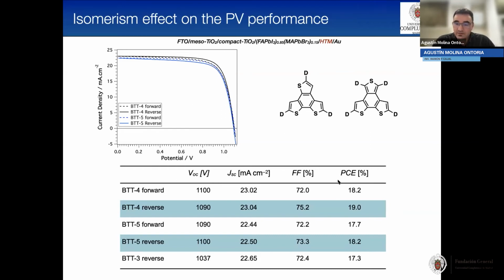Well, the results are collected in this table. As you can see here, BTT4 exhibits a 19% efficiency, and BTT5 exhibits 18.2%. Both of them exhibit better efficiency than their analogous BTT3 that was previously reported. So why is that? We surmise that it is because the sulfur atoms are facing in the same direction, so they may further interact with the perovskite, allowing better hole extraction.